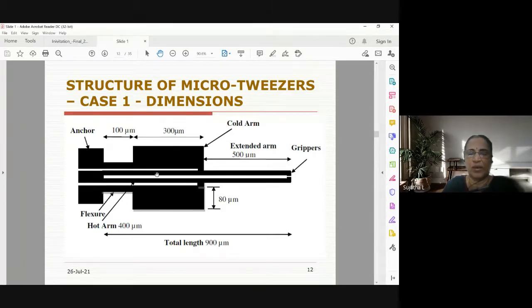width of the hot arm, if it is very thin, actually it is 20 micrometer. The width of the beam is 20 micrometer. The thickness is 10. For the lateral movement, the aspect ratio of the width with respect to its thickness should always be high. So we have taken 20 micrometer as width because the SOI wafers come with a device layer thickness of 10 micrometer. The top layer of the silicon SOI structure, I'll show you in the next slide. So the SOI structure's top device layer is silicon. The thickness of that SOI layer is 10 micron. So we kept the width of this hot arm as 20 micron, and this one as 80 micron.